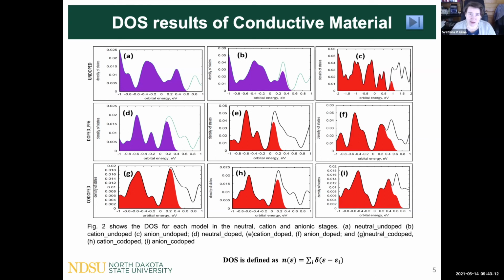Okay, so the gap really depends on the functional which you use, and GGA functionals are known to underestimate the band gap for semiconducting materials. So usually they do not agree with experiment. It would be really surprising if they did. It is the common failure of GGA functionals such as PBE that they make the gap smaller compared to the actual one. And there is a reason, but I will probably stop the discussion here. This reason will probably be another question to another student.